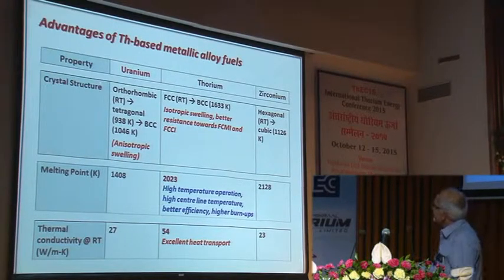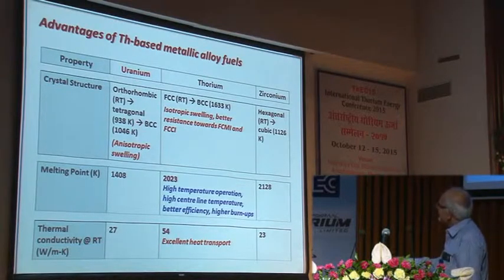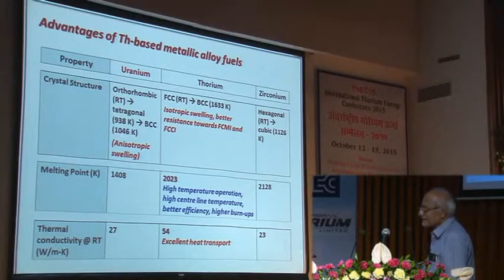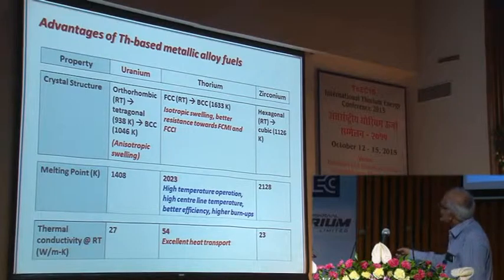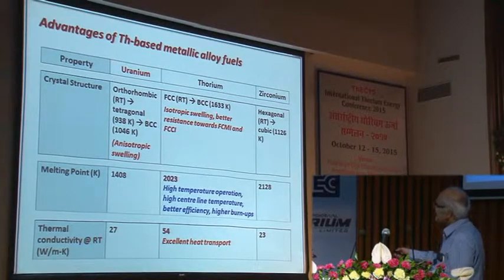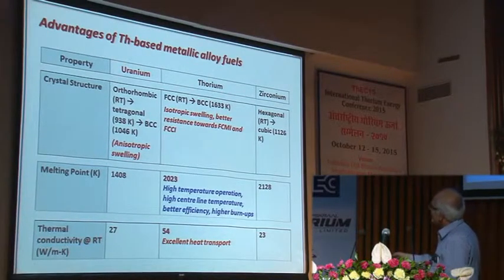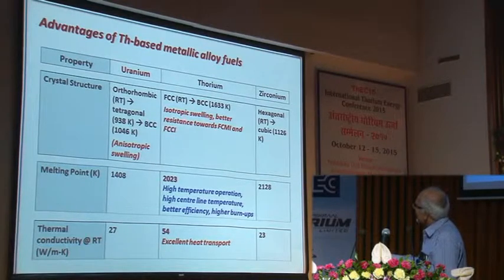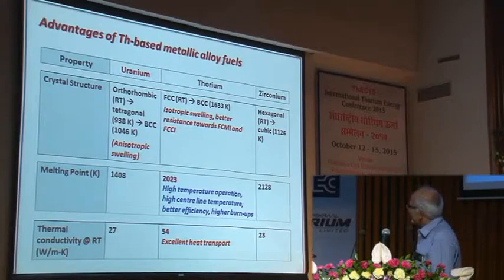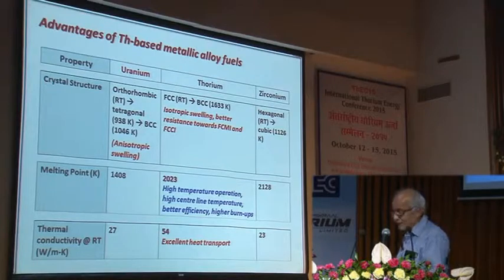If you take the crystal structure, this is compared for uranium, thorium, and zirconium. In uranium, from room temperature to 1000 degrees Kelvin, there are so many phase transformations which take place, whereas in the case of thorium, it is from FCC to BCC at 1633 Kelvin. So there is an isotropic swelling, and it's a better resistance towards FCMI and FCCI. The melting point is higher, so you can have high temperature operation, high central line temperature, better efficiency, high burn up. Thermal conductivity is good, so it's excellent heat transport.